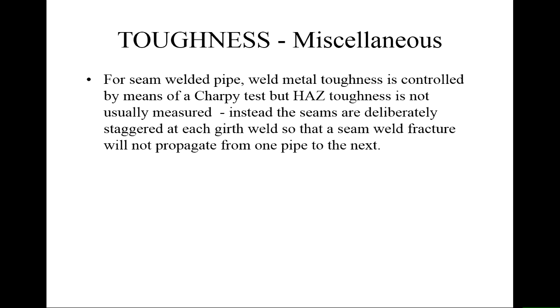Secondly, welding consumables introduce more elements into the weld pool, and some of those over a period of time can end up diffusing into the heat affected zone, and you might find that there is an influence from that. The real problem with it is getting your Charpy test with the notch in the heat affected zone, and so there's a bigger variability on where the notch gets positioned than actually the variability that it would cause.